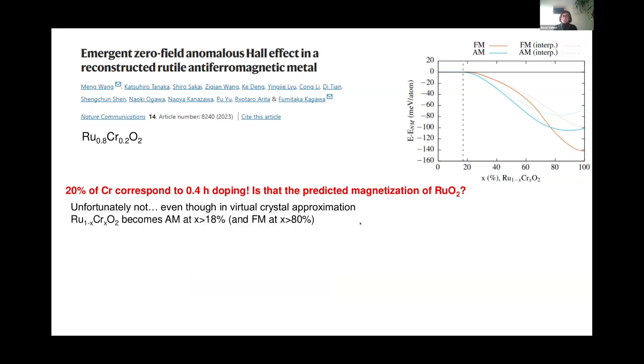the virtual crystal approximation is not always a good approximation. So what do you do in the virtual crystal approximation? Basically you start with your unit cell for your ruthenium dioxide in this case, and what you do then is artificially change ruthenium by a mixture of ruthenium and chromium, so by an artificial atom, and you redo the calculation. So this would mean, if you do this type of calculation, that you are assuming that you have a completely uniform doping of the system.